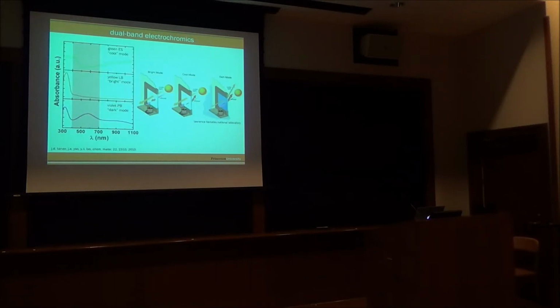So where are we headed? At the outset, I said that polyaniline has multiple different oxidation states, and we've only used the extremes, the reduced and the oxidized oxidation state, and that's shown here. Right? There's this green emeraldine salt oxidation state that's quite interesting because it doesn't absorb a whole lot in the visible, but it absorbs in the near infrared. So you can access this cool mode where you're absorbing infrared, but you're letting visible light in. So that's where we're headed.